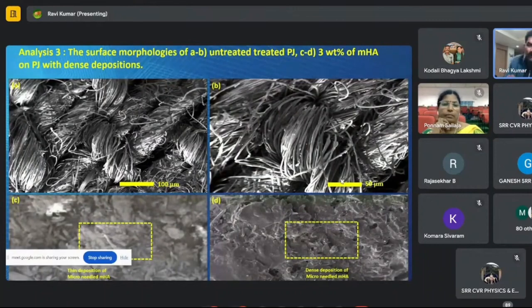You can see the jute fiber mat under magnification, showing the surface morphologies. Images A and B show a clean surface because there is no deposition on the surface of pure jute. These look like hairs, and there is no foreign body on the surface. But in the case of C and D, you can find the deposition of MHA on the surface. There are no gaps on the surface in images C and D. It means dense deposition occurred after dip coating, with 3 weight percent of MHA on the jute, and you can find the dense depositions in the SEM images.